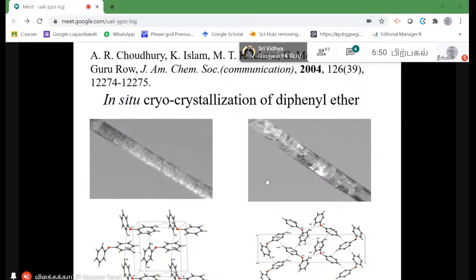What you do is take diphenyl ether, which is a liquid at room temperature, put it in a capillary, and mount it on the diffractometer, and then use liquid nitrogen to cool this region of the capillary. We control the rate of cooling, and depending upon the rate of cooling, we get a crystal. The way in which we grow the crystal is by doing what is known as variation in ramp rate. We heat and cool, keep on repeating that process.